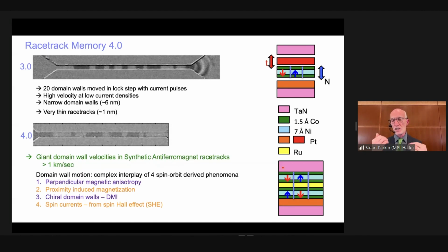And this concept of a synthetic antiferromagnet was also used in IBM's very first spin valves. It's the only way to build nanoscopic magnetic devices. Otherwise, they have too strong magnetic interactions through these dipole fields. This is just to point out that in order to build these structures, we need to use techniques that enable us to deposit angstrom thick layers over very large wafers, 300 millimeter wafers, to build racetrack memory technology.